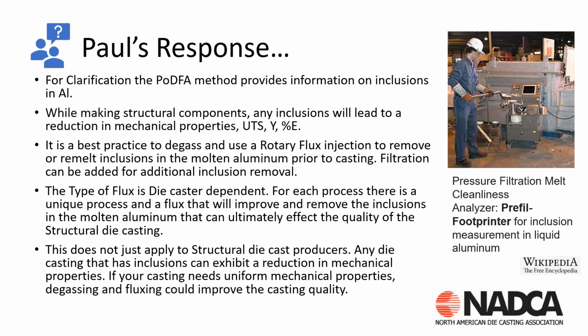The type of flux that a die caster can use is die caster dependent. For each process, there's a unique process and a flux that will improve and remove inclusions in the molten metal. Inclusions do not apply to structural die casters only. Any die casting that has inclusions can exhibit reduction of mechanical properties. So whether it's the structural die casting or standard die casting, if you need uniform mechanical properties, then you can use flux and degassing methods to improve the casting quality.